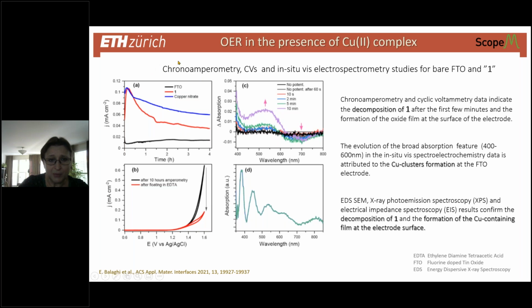Now, chronoamperometry and cyclic voltammetry, as well as in situ electrospectrometry results, indicate that the compound, which I call compound 1, or bold 1, for simplicity because it's a large formula, starts to decompose already after a few minutes after we run the current through the electrolyte containing this compound. If your electrode in the electrolyte without the compound shows pretty much constant current density, then when we add the compound, we have quite a different performance: the current density, after a quite good and promising value, drops promptly to about 40 microamps per square centimeter.